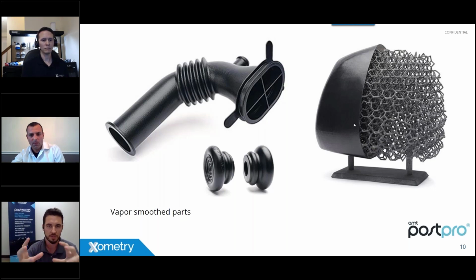But the benefit of not only taking a flexible material but chemical vapor smoothing is that we can smooth and seal the material, and it's a non-line-of-sight process, meaning we can get the inside of these complicated lattice structures or through the through hole of this flexible tubing with the chemical to evenly smooth the inside and the outside of the part equally. If you were to do this traditionally, good luck trying to get your hand inside the lattice structure to sand it, or inside that tubing to sand completely, and then just to smooth it, right?